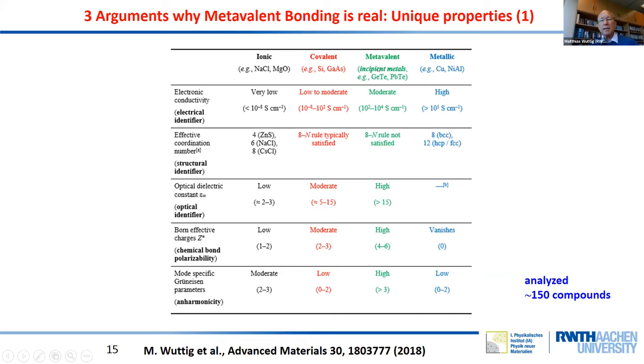And then you realize that these metavalent materials have a distinct set of properties. Importantly, their properties are not a linear combination of any other property fingerprints that we have. You can see this, for example, from this mode-specific Grüneisen parameter. That's a measure of the anharmonicity. This is high in these materials, but it's low in both covalent and metallic systems. So the properties are telling us these materials are unique. Their region in the map tells us these materials are unique and they have a unique bonding mechanism.